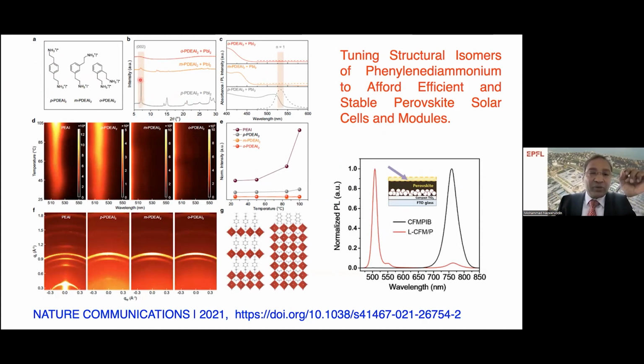this is a characteristic XRD peak of the two-dimensional perovskite, which comes around 6.5 2 theta. So the para-containing cation is forming the two-dimensional perovskite. Correspondingly, you can see the spectral properties, the absorption spectra of the two-dimensional perovskite, and the emission spectra, which is coming very close to 550 nanometers. However, if we go to the meta and ortho, it's not forming the two-dimensional perovskite, and there is no emission spectra. The absorption spectral properties are also quite different.